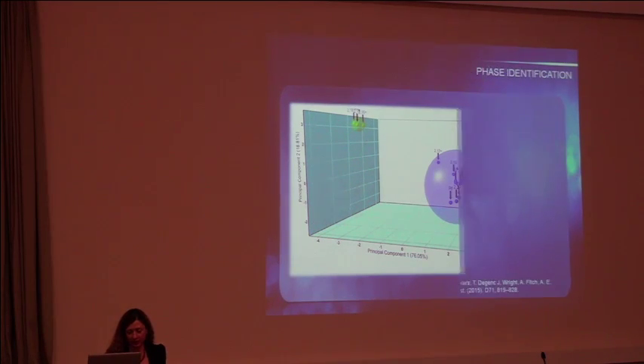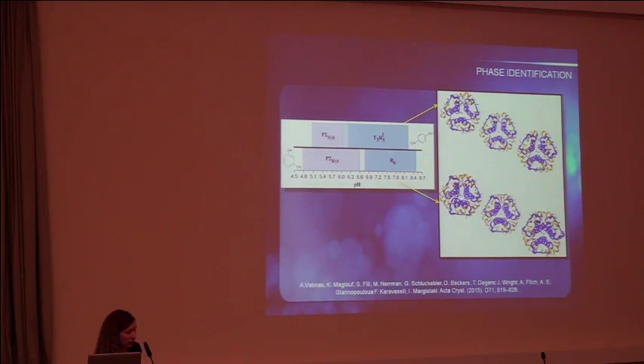After indexing, we knew that there is a clear phase transition in both cases of ligands. With m-cresol, we have a transition from a monoclinic phase, previously unknown, to a hexagonal phase, the R6 molecular conformation. With 4-nitrophenol, we have again this new monoclinic phase appearing, and at high pH, we have one of the known hexameric forms of insulin.